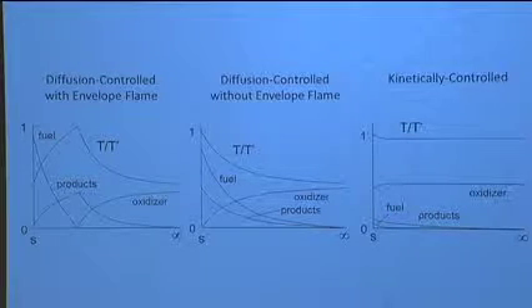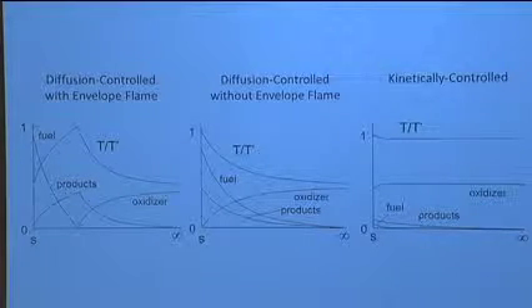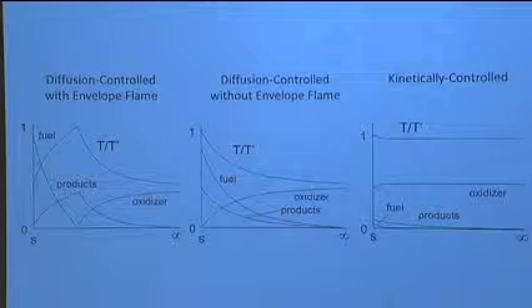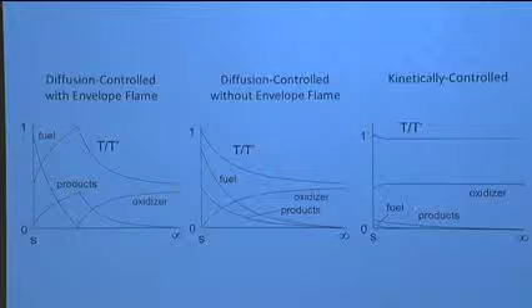So now I ask another question. Suppose the environmental temperature is less than the vaporization temperature. How's aluminum going to burn now, at a nanoparticle? So I'm going to have another two regimes here, depending on whether the environmental temperature is above the vaporization temperature or below the vaporization temperature. And it's going to be totally not constrained by what the particle's doing itself.